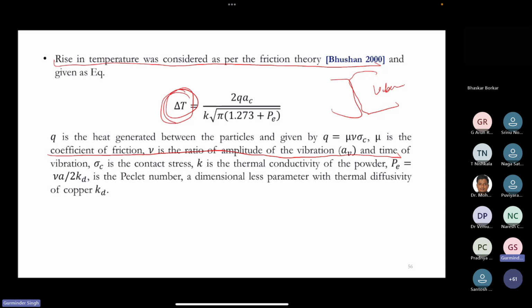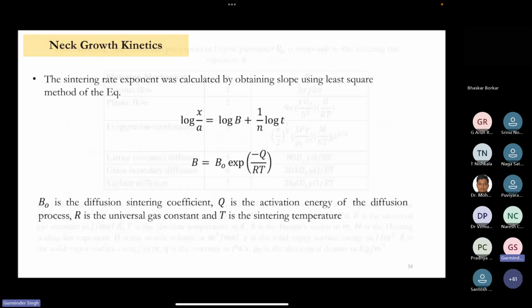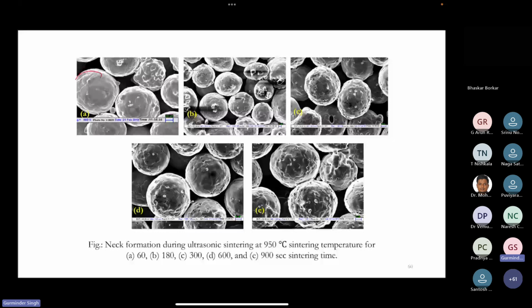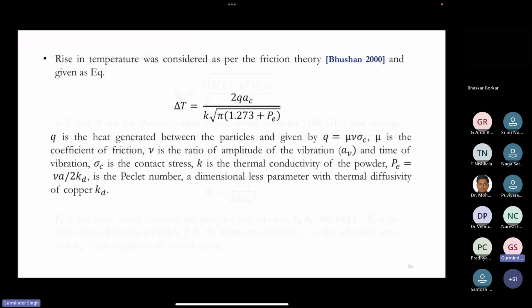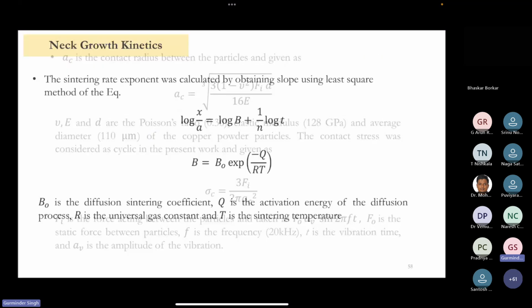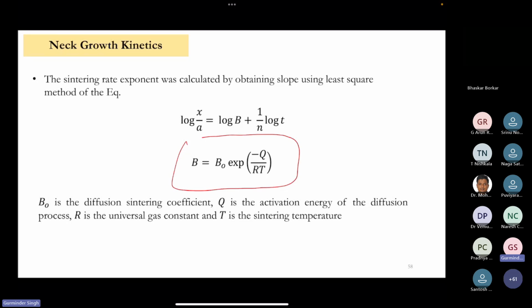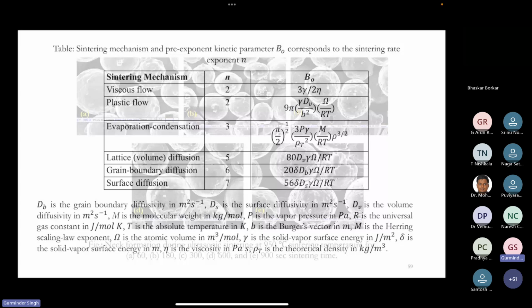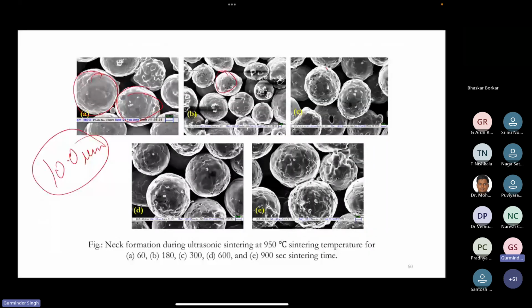It depends on the particle size. So we have kept particles which have the same shape and the same size, about 100 micrometer, so that we can effectively find out the values. We have added this delta T in the main formula, and we tried to measure it experimentally. We have done a number of experiments like this one, at different temperatures and at different times, and we have calculated this x value and this a value. It's a 2a diameter.